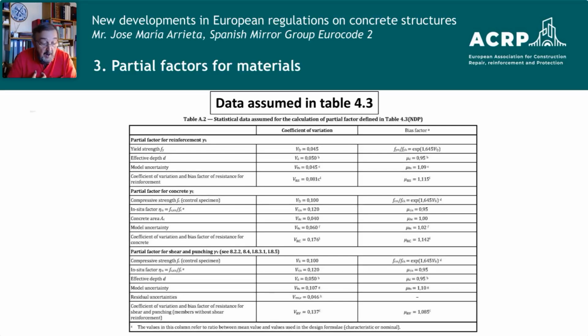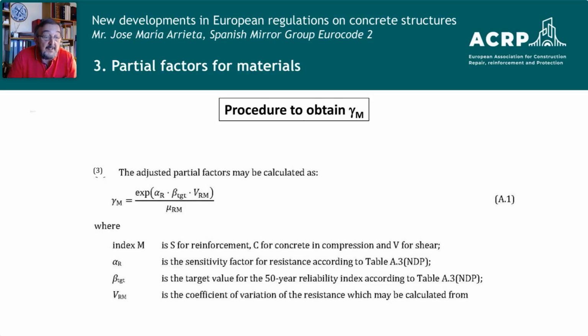That means that if our statistical values are different, as there is a procedure to calculate this gamma coefficient, we can modify this coefficient if, for example, our production of concrete has a coefficient of variation less than 0.10, as is supposed. This expression is all developed in Annex A. We can see the different variables: the sensitivity factor, which usually is 0.8, the beta target, the reliability index, which usually is 3.8, and the coefficient of variation and the bias factor of the resistance. With that, we can recalculate this coefficient.